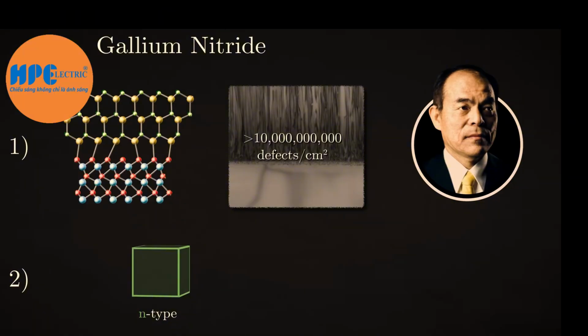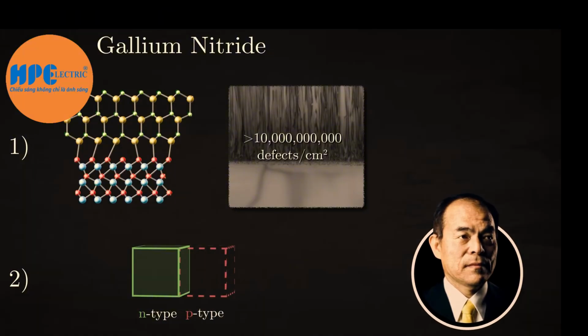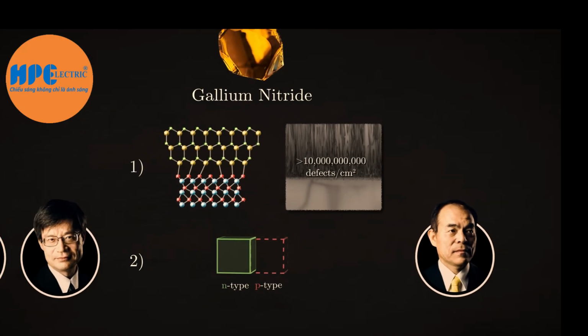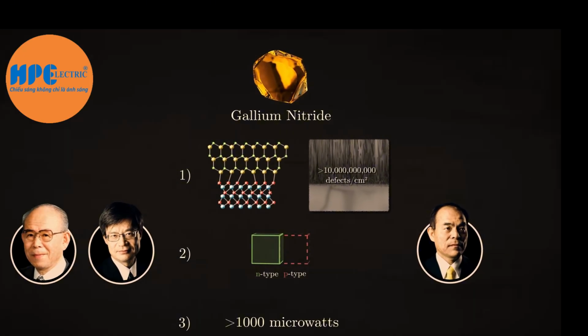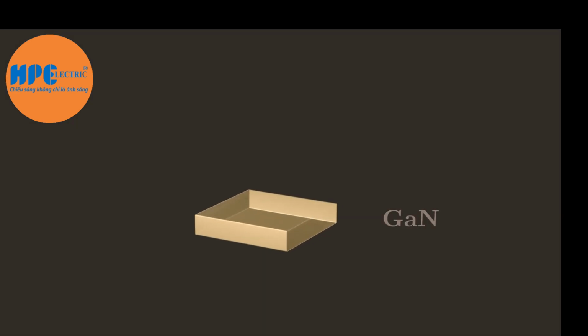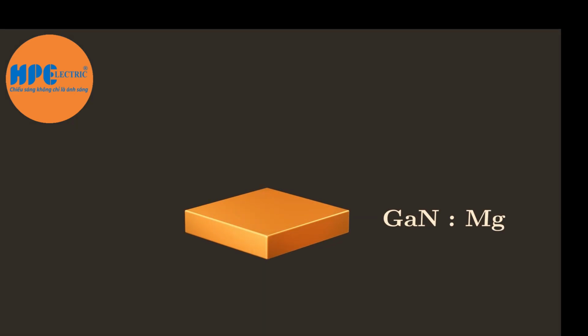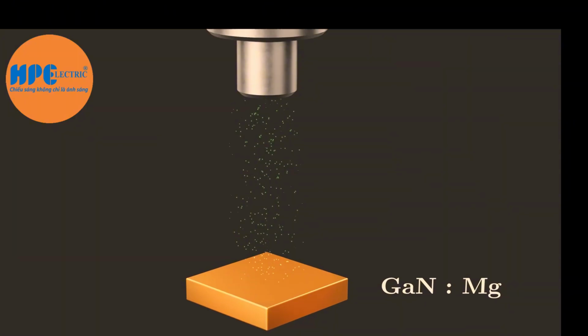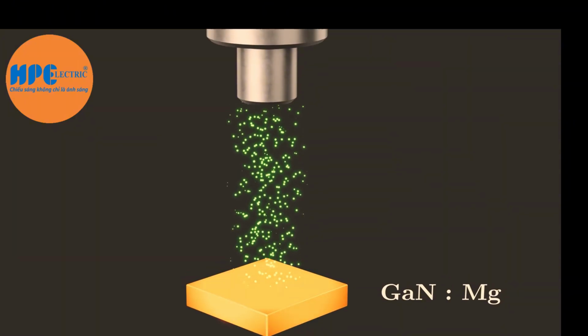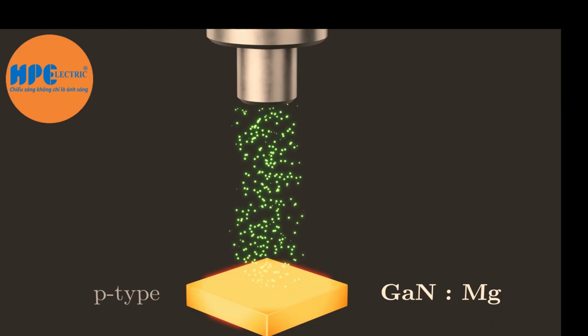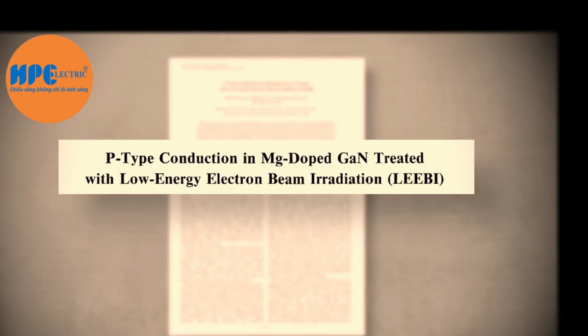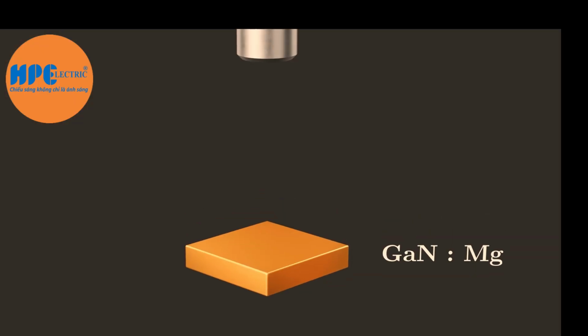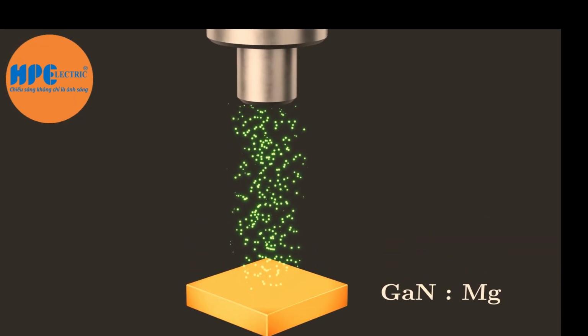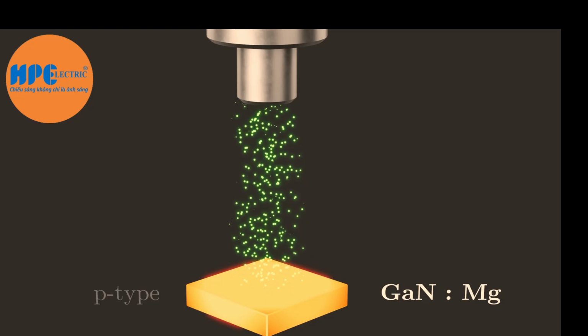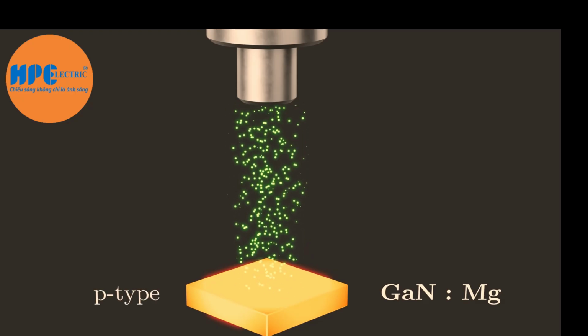With crystal formation settled, he turned to the second obstacle, creating P-type gallium nitride. Here, Akasaki and Amano had again beaten him to the punch. They had created a gallium nitride sample doped with magnesium, but at first it didn't perform as a P-type as they expected. However, after exposing it to an electron beam, it did behave as a P-type, the world's first P-type gallium nitride after 20 years of trying. The catch was that no one knew why it worked, and the process of irradiating each crystal with electrons was too slow for commercial production.